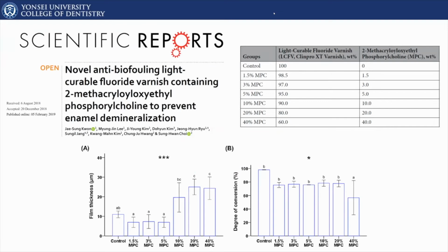So we incorporated this MPC, one of the zwitterionic materials, into very simple materials like light-curable fluoride varnish. This is how we added it. Different contents of the MPC were added into light-curable fluoride varnish. As you can see here, at low contents of this MPC, the physical properties are pretty well maintained, as well as the degree of conversion, even at 20% MPC.